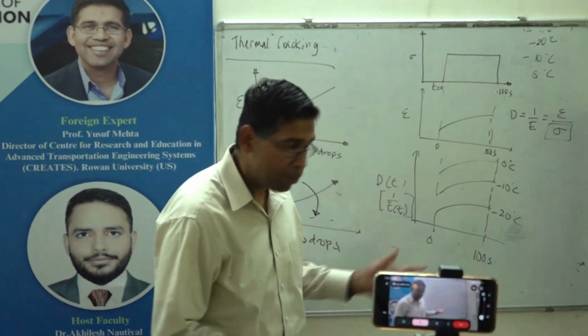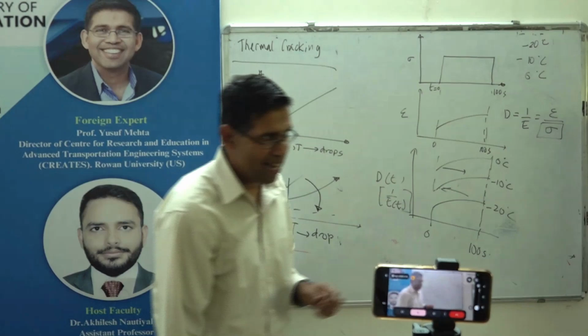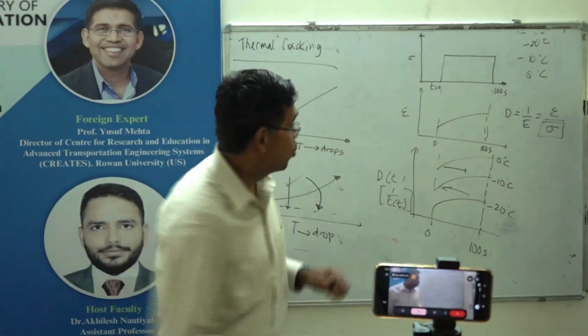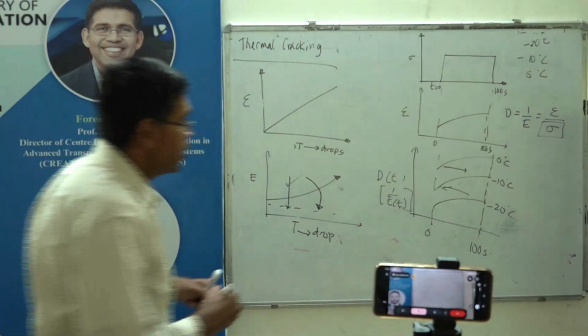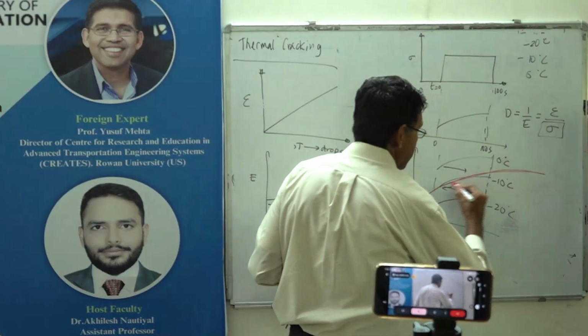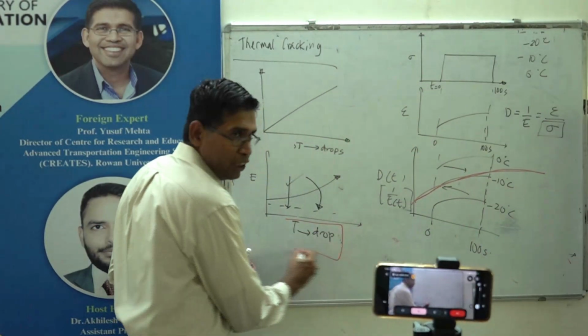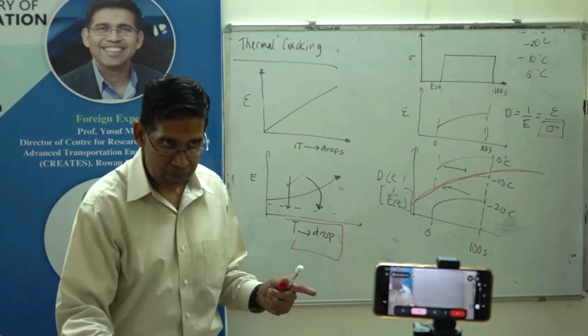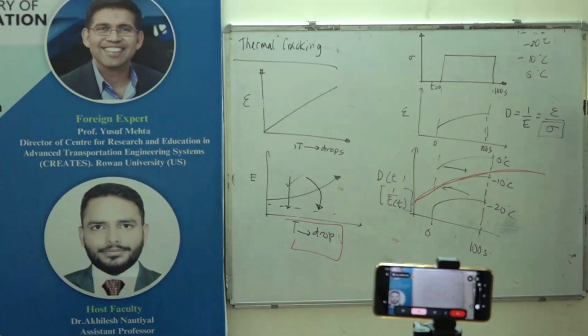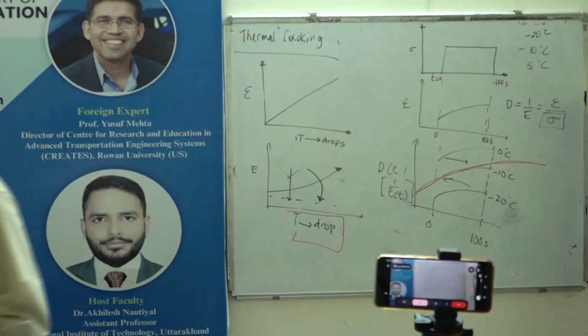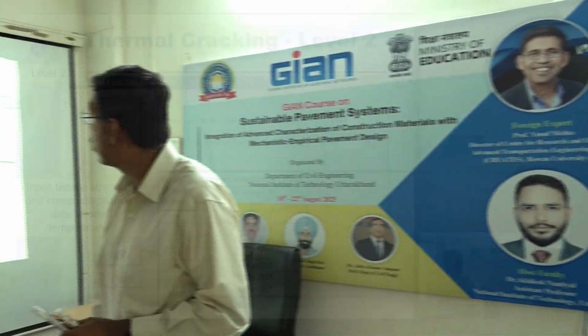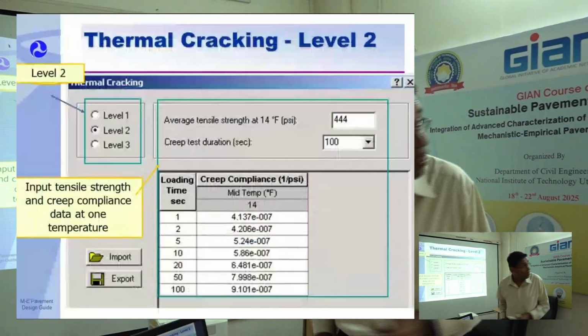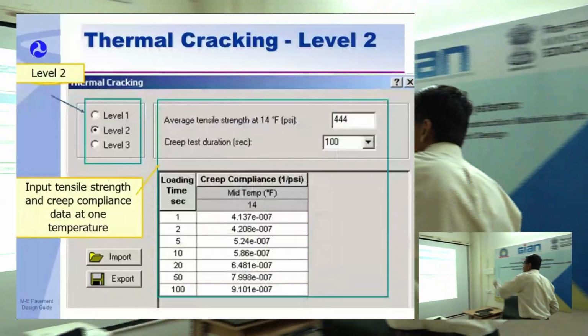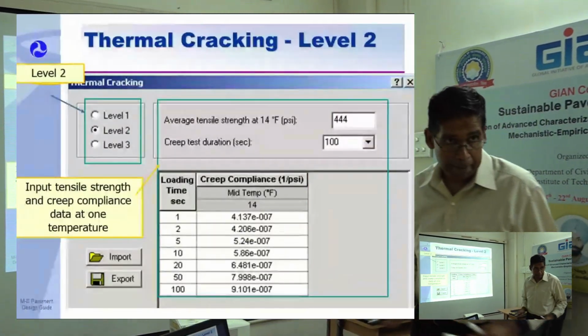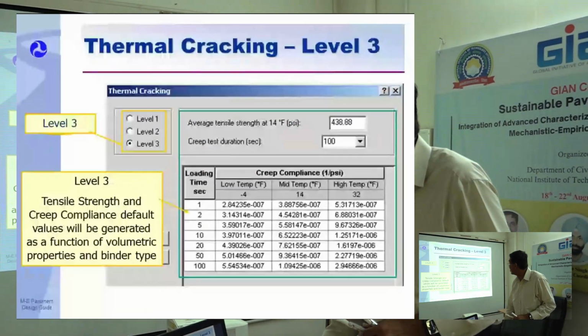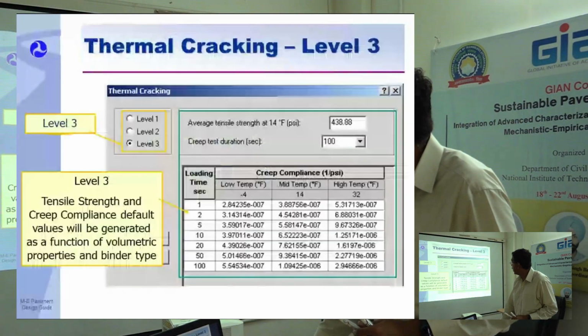Now you can do the same thing, time temperature superposition, all of that is exactly the same. That's what the 3 data sets are for. So I can now calculate this master curve with time, which I can translate to temperature, which I just explained to you. Time and temperature are interchangeable. So if I get the time, I can easily change it to temperature, and this is what I'm trying to do. Right here, you got that, and then you also get the strength. That's where it breaks, and the strength at minus 10 is 444 psi. Get your compliance, get your data, and that's how you get your critical temperature.